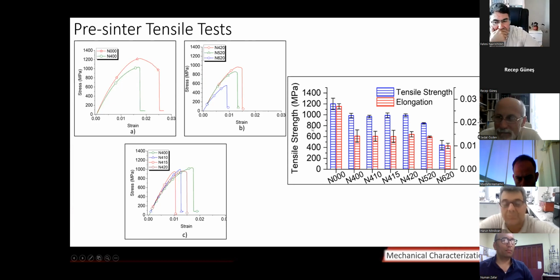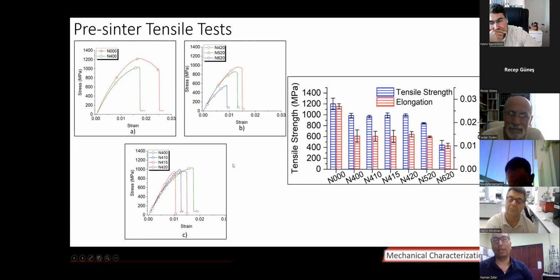Yes, yes, sir. Here I have shown the influence on pre-sinter wires' tensile behavior. The diameter of the core is the most influential factor which changes the tensile behavior of the wires. But when you go from 420, 520 to 620 and increase the core diameter, the tensile strength and tensile strain both decrease.